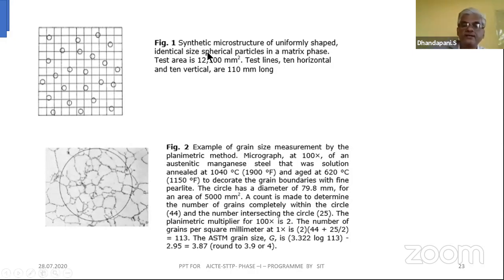For that, the circle diameter is given as 79, and the area is given, and the count is made to determine the number of grains completely within the circle. So within the circle, the number of completely inside grains is 44. The number intersecting the circle is 25, grain boundaries intersecting as already told. And then the planimetric multiplier: planimetric is a method. For 100x magnification scale, the multiplication factor is 2. There is a standard table, and they will take the value. The number of grains per square millimeter is 113.